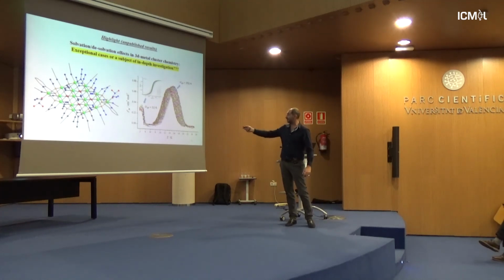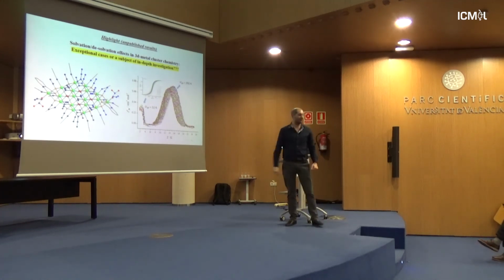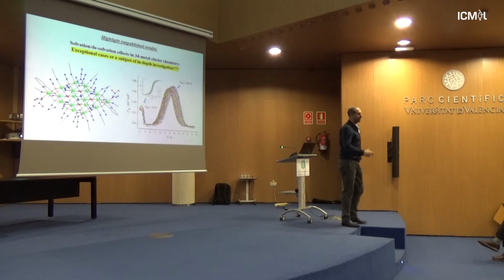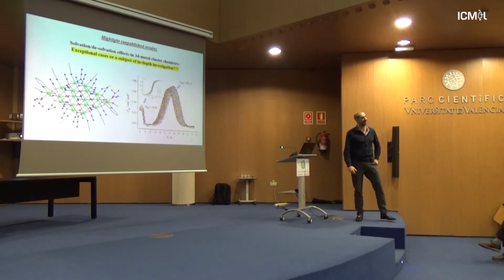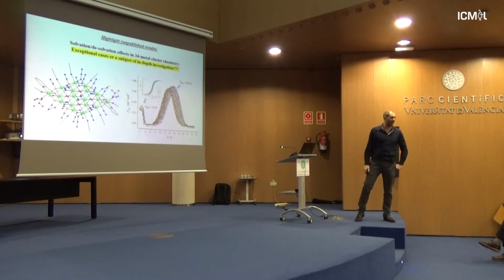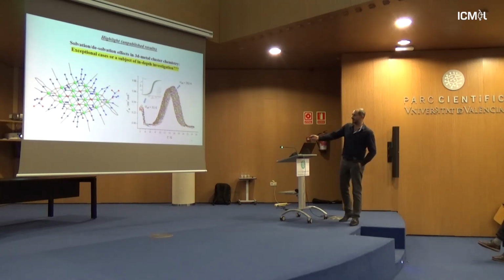First process at around 20 Kelvin with a barrier of 400 Kelvin, by far the largest barrier in 3d metal cluster SMMs. It's an unpublished result. It's the first time that I show it to the community. And the second relaxation here is more intrinsic to the molecule itself.